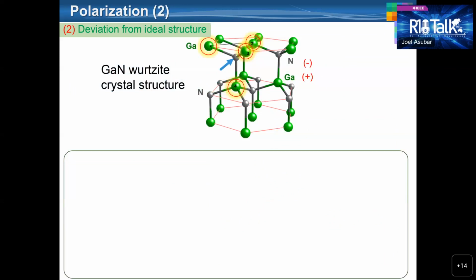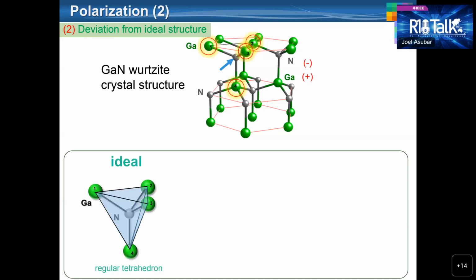The second reason for the polarization is the deviation from the ideal structure of the gallium nitride wurtzite crystal structure. If this is the gallium nitride wurtzite crystal structure, we can construct a tetrahedron considering these 1, 2, 3, 4 gallium atoms as corners and this nitrogen atom as the middle atom, like this. For a regular tetrahedron, all the 4 triangular faces have the same area. This is for an ideal regular tetrahedron. However, for the actual gallium nitride structure, this is not the case.